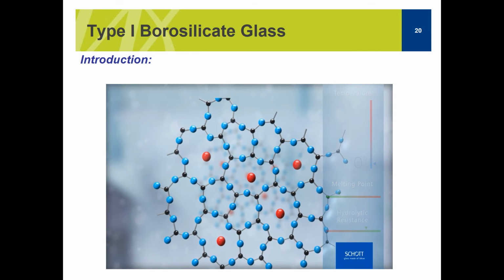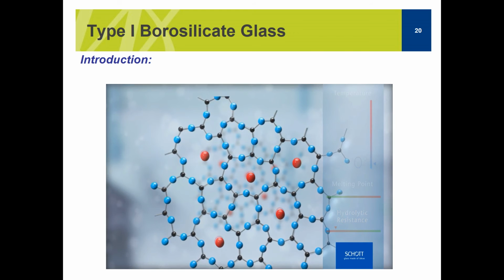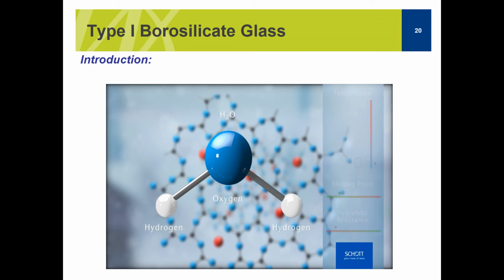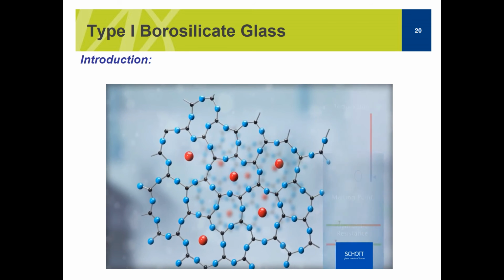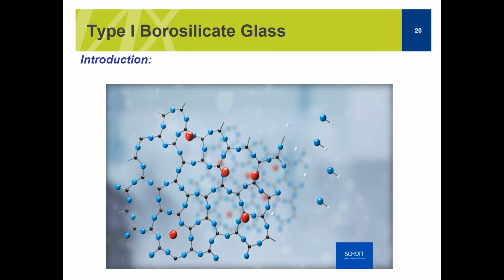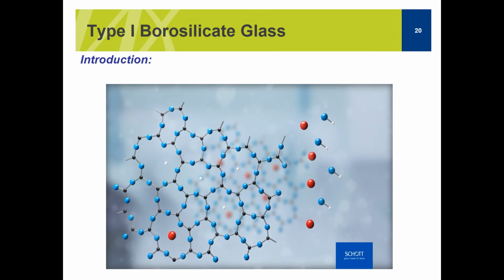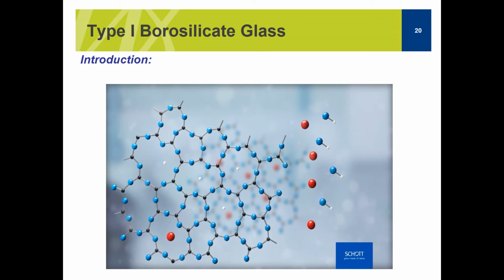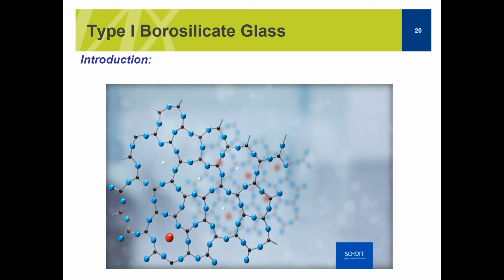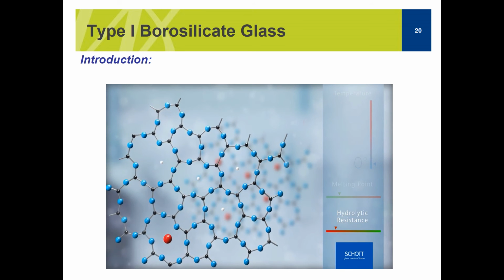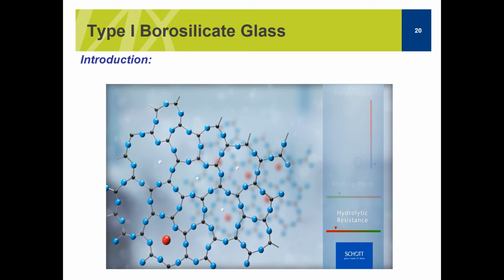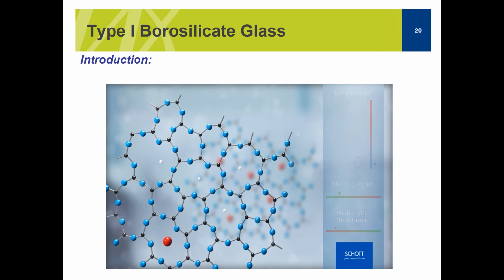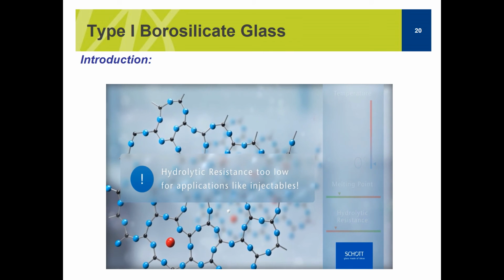A disadvantage of adding network modifiers is that they also decrease the hydrolytic resistance. This means that there is more reaction with water. Water consists of an oxygen with two hydrogens. In contact with water, the glass surface exchanges a network modifier for a hydrogen. In this case, one sodium goes into the water and one hydrogen goes into the glass. The more network modifiers are removed from the glass, the lower is the hydrolytic resistance.